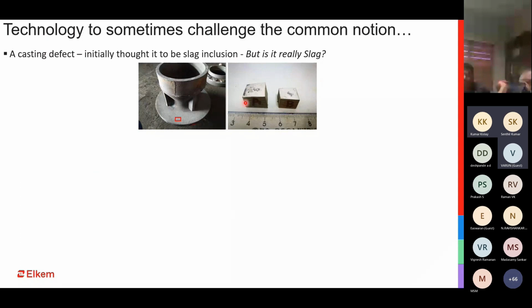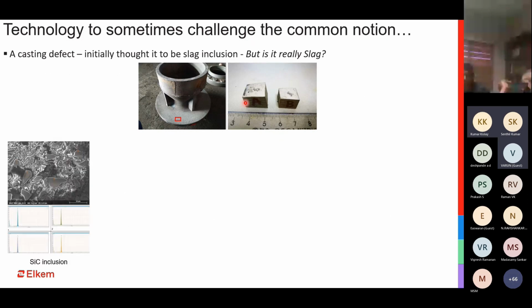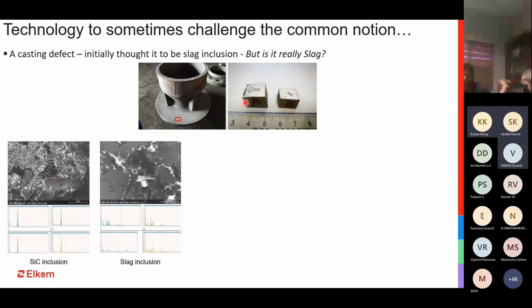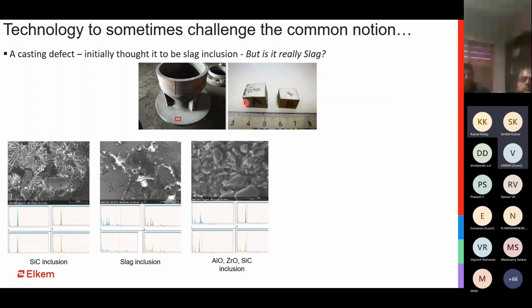So when we looked into the casting using the SEM and the EDS that we have with us, we identified some silicon carbide inclusion. We identified some slag inclusion. So yes, the foundry was not completely wrong. They did have some slag, but it was not just slag. We identified some aluminum oxides, zirconium oxides, and silicon carbide inclusion. Where would this come from? Probably from a broken filter. That's possible. And the broken filter itself might have caused slag inclusion because it was not able to trap the slag in